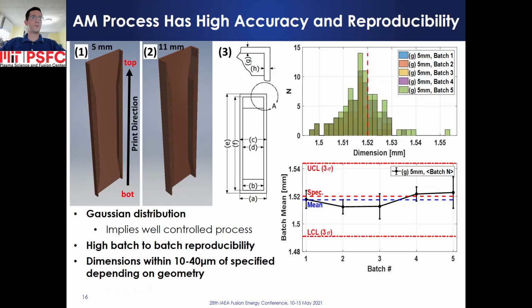Laser powder bed fusion results in both high accuracy and high batch-to-batch reproducibility. A Gaussian distribution of dimensions indicates a well-controlled process. Low variation of distribution mean between batches indicates high reproducibility with negligible effects of operator setup. Actual dimensions typically fall within 10 to 40 microns of the specified dimension depending on geometry.